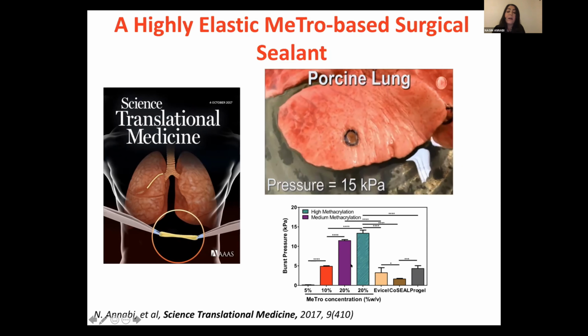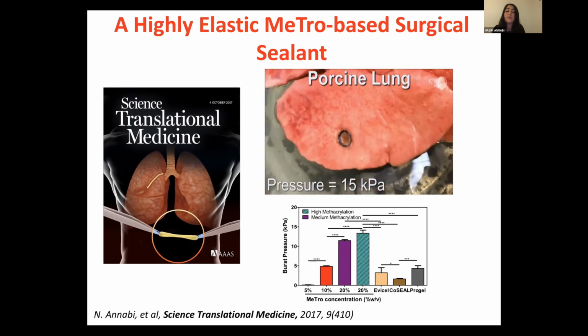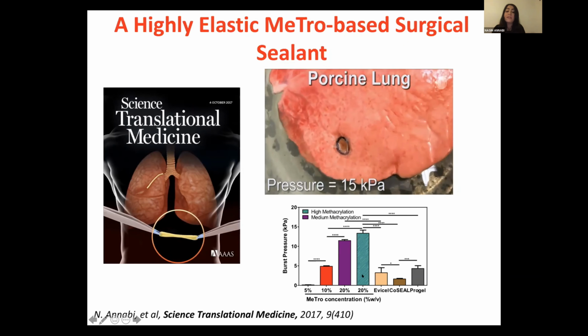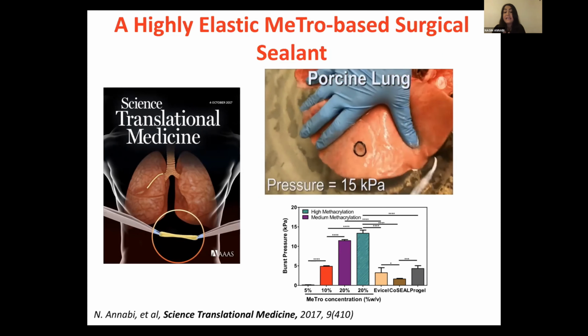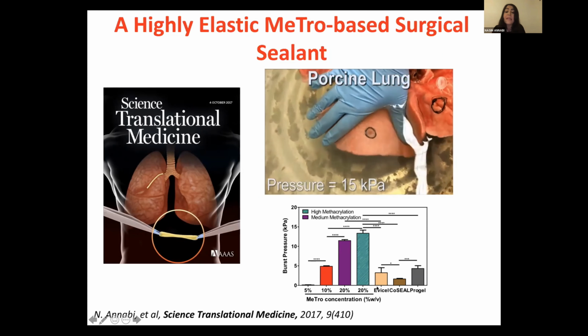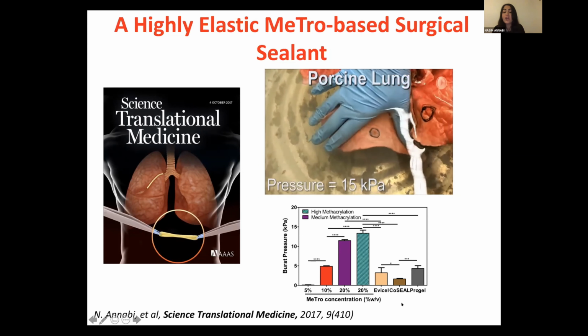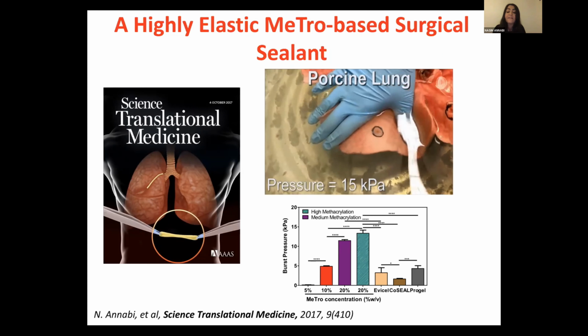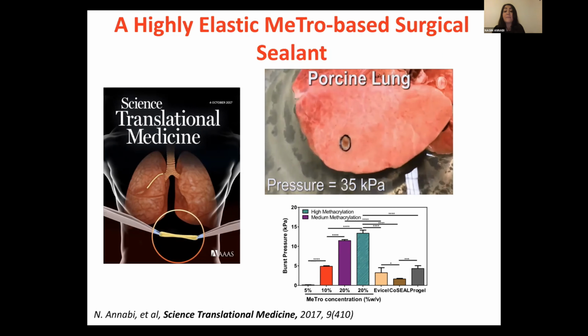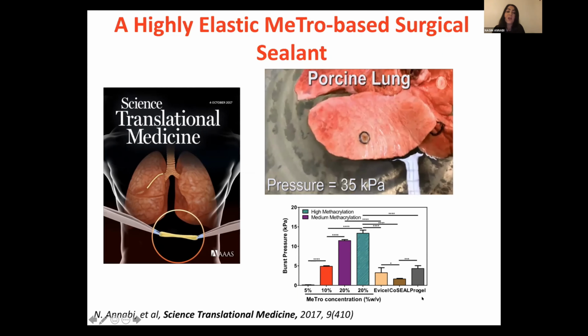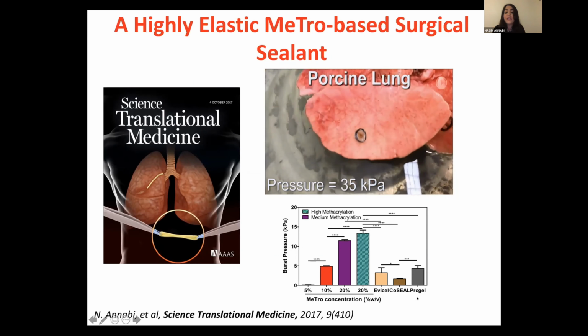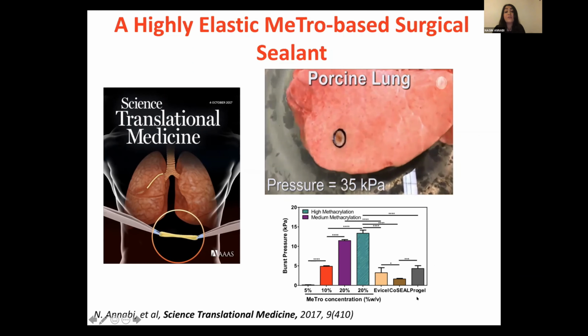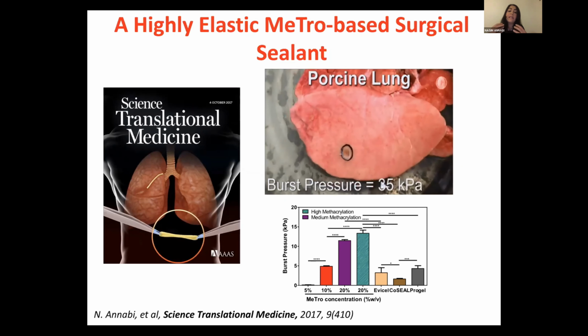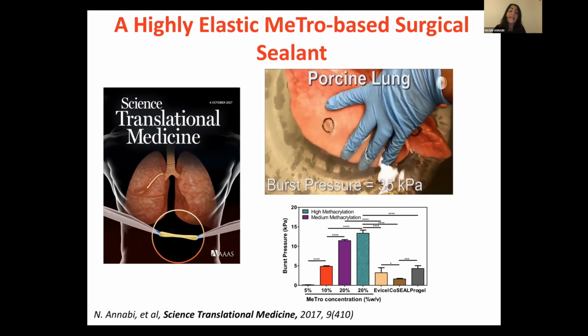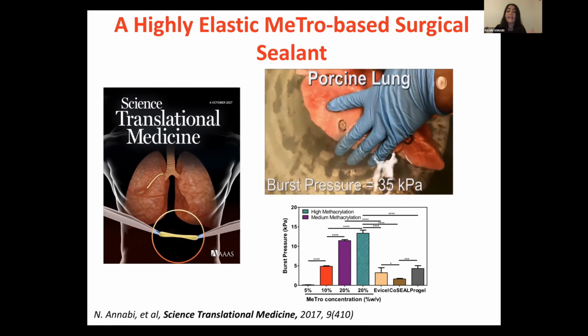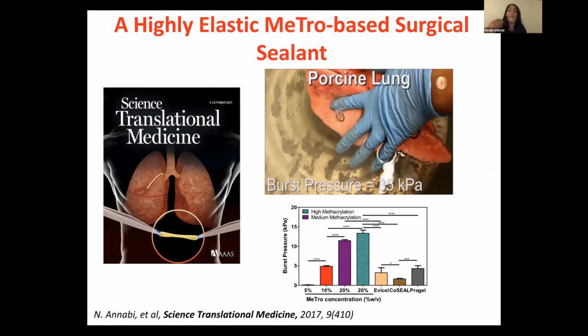We modify the formulation of the Metro to improve its adhesion properties to wet surfaces. And here in this experiment, our indication was lung. And then we also purchased different types of commercial glues such as Progel, CoSeal, and Evicel. Evicel is a fibrin glue. CoSeal is a PEG-based glue, and Progel is based on a PEG linker and human albumin. And Progel is the only FDA-approved one that surgeons use for lung surgery. And unfortunately, following the application of Progel, the patients remain with extensive air leak, which can extend the days that they have to spend in hospital after they go through lung surgery.